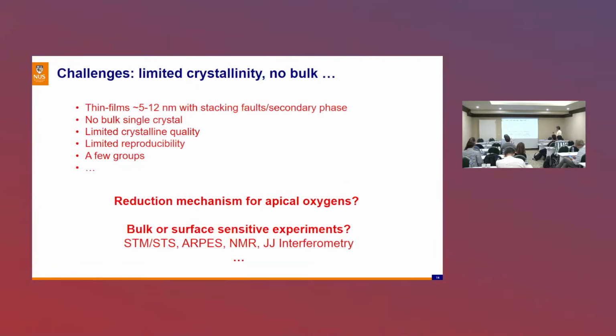So what is really the challenge from the experimental point of view, all right? As I demonstrated before, all of those data are simply based on thin film samples with a thickness ranging from 5 to 12 nanometers. And even for these samples, you are dealing with many different issues with crystallinity. You have stacking faults, secondary phases, and so on, that you really need to take care of before you can make conclusions based on the experiment that you do.